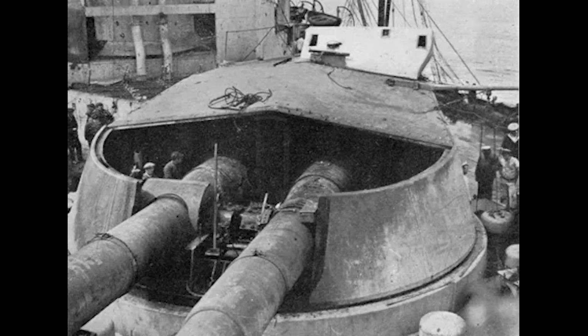The British and Germans made fundamentally different choices in their armor development, and understanding these choices illuminates why American armor became inferior. British armor manufacturers, testing their armor with British projectiles during the 1920s and 30s, maintained thinner face layers. British armor from this period typically featured faces comprising approximately 35 to 40% of plate thickness, substantially thinner than contemporary American armor. Surface hardness remained in the range of 550 to 600 Brinell, hard enough to provide protection against armor-piercing projectiles, but not so hard that the face became excessively brittle.